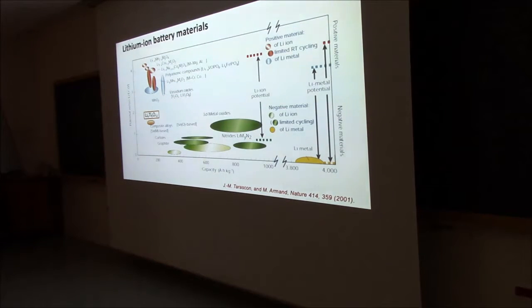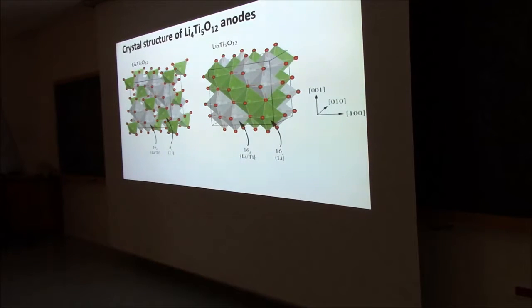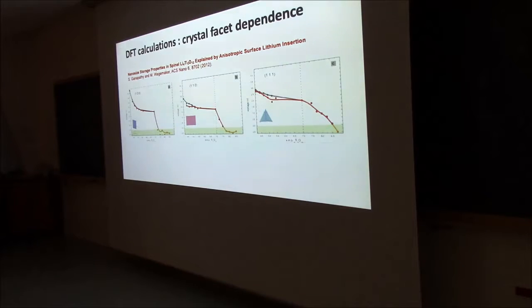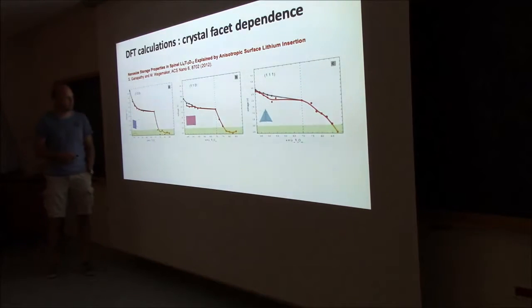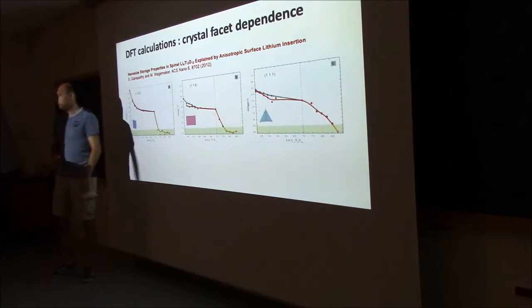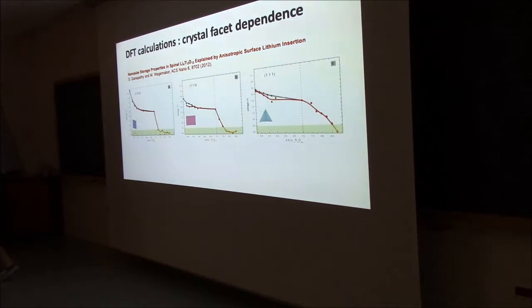So we said, okay, let's see what we can do there. And there, lithium is not in a layered structure, but it's also a spinel. It's an inverse spinel, and there you can go from a lithium 4 situation to a lithium 7, and you go back and forth between these two. The prediction was, from a colleague of mine at Delft University, that if you have a specific orientation, a specific crystal facet, at the surface you would also be able to attach a lot of lithium. Where you could go to, I said, you go between lithium 4 and lithium 7 in these two materials.